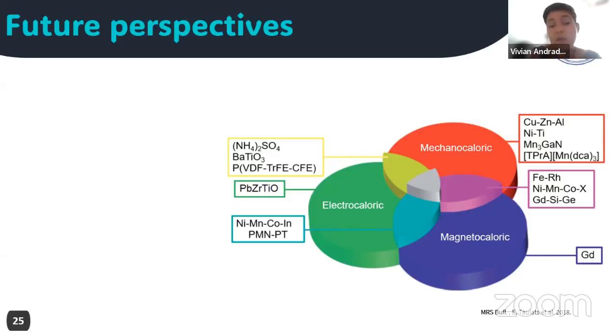Yes. I didn't talk much about the materials. I could have, but I thought I wouldn't have time to talk more on this. But gadolinium is the reference material when we talk about the magnetocaloric effect, because it has a transition of second order. So it does not have a structural change from one magnetic order to the other. As I mentioned, the milestone for the magnetocaloric effect was the discovery of the giant magnetocaloric effect in gadolinium-5 silicon-2 germanium-2. So after this discovery is when we have more production of prototypes. But they are also based on rare earths.